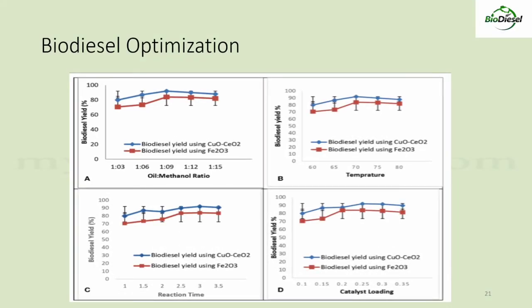Biodiesel optimization was also performed for four different parameters. The first one is the oil to methanol ratio, the second one is the temperature, the third one is the reaction time, and the fourth one is the catalyst loading. The result shows that the highest yield of biodiesel was obtained at a 1:6 oil to methanol ratio, that was about 92%. The temperature was about 70 degrees, reaction time is 3 hours, and the catalyst loading is 0.25%. These optimized conditions produce the maximum biodiesel yield, that is 92%.